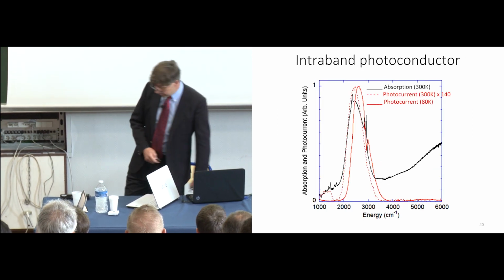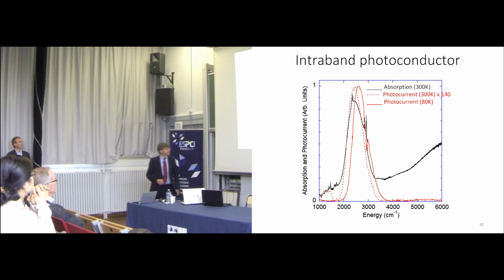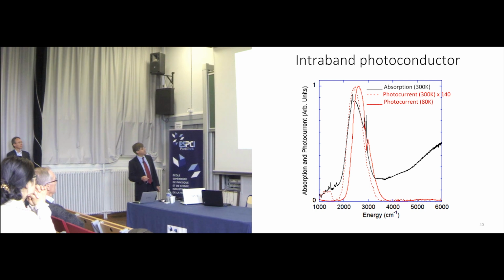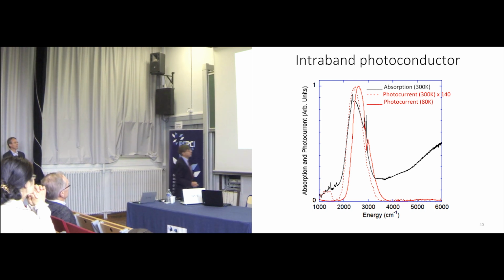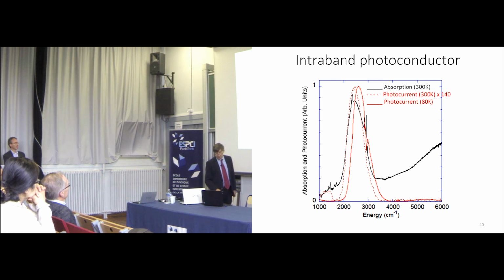And so this is our first intraband photoconductor. So we take those kinds of materials and we can measure, in good cases, we can measure room temperature photoconductance. And now you see it's just a peak. It's not a broad absorption with an edge. It's just a single peak where the intraband transition is. And at low temperature, we get a very decent signal to noise.